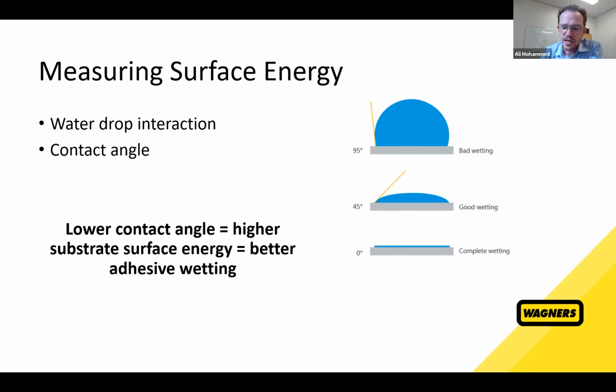On the right, you can see a water drop on a substrate and how it interacts under various wetting situations. On the top, you've got bad wetting, whereby the water drop does not flow on the surface and doesn't wet it out. It sits almost as a drop entirely on the surface. In the middle, you've got what we call good wetting, where the drop has flowed out and wet the surface, and the bottom is obviously very, very good wetting. Now, to standardize this, they measure the angle between the water drop wall and the surface. That angle is given the name contact angle. A high contact angle, which you can see in the top one, is a representation of bad wetting, whereby the drop hasn't flowed, and a low contact angle indicates very good wetting or very high surface energy, where the drop has flowed across the surface.